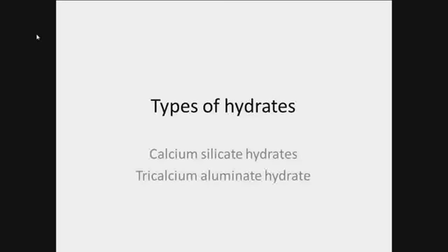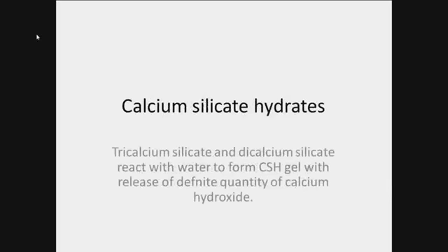When water is added in a limited quantity, as in the case of cement paste or cement concrete, tricalcium silicate undergoes hydrolysis first. That is, among the dicalcium silicate C2S and tricalcium silicate C3S, C3S is the first to undergo reaction or hydrolysis, producing calcium silicate of lower basicity. Ultimately, C3S2H3 or CSH gel is produced, and lime, that is calcium hydroxide, is released.